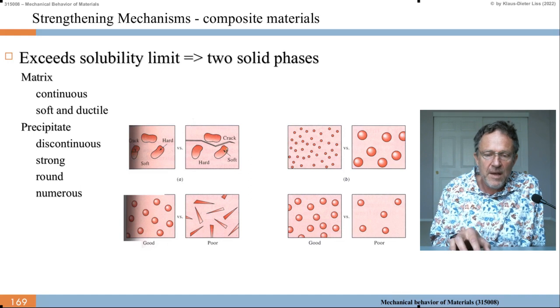So this becomes poor. Also, if the included material here is soft, you see the crack can go through like that. If it's hard, then the crack would be held by the hard material. So if the crack goes through here, it just goes through the soft material. But if here a crack goes through the soft matrix, it may hit a hard precipitate, and that makes the properties better.